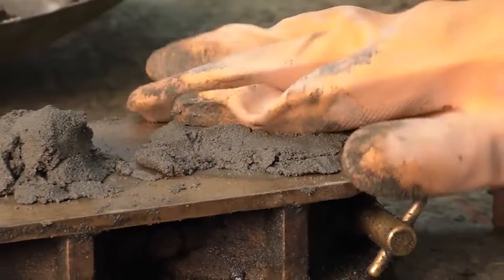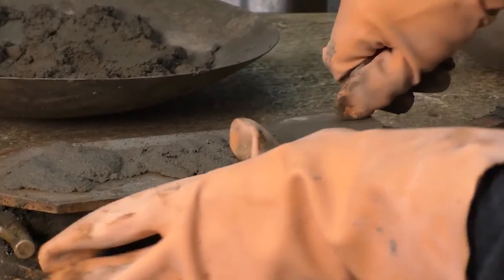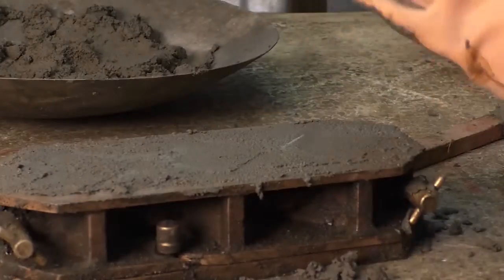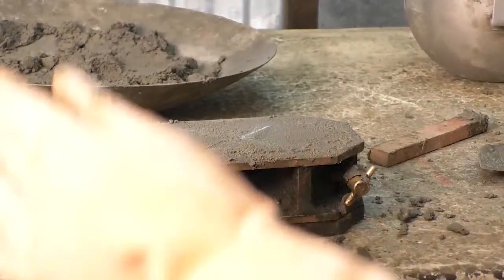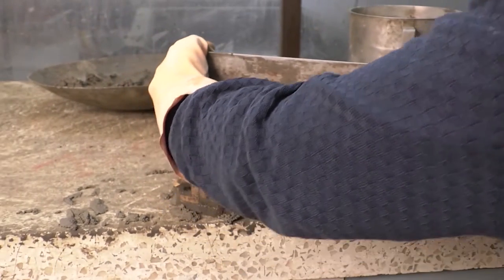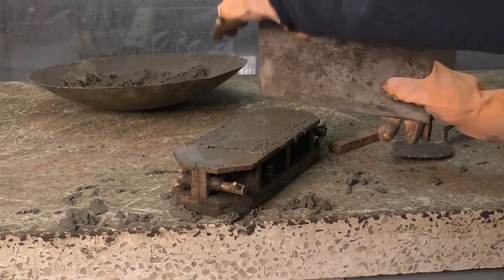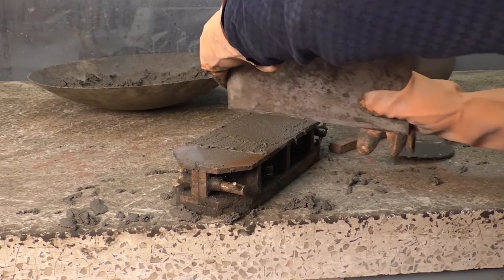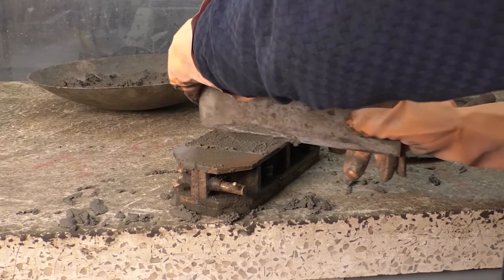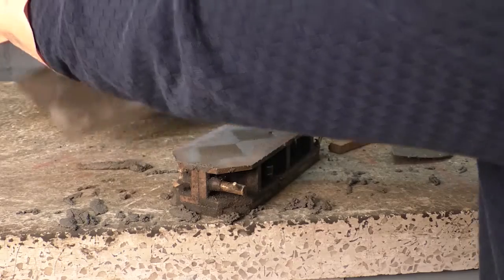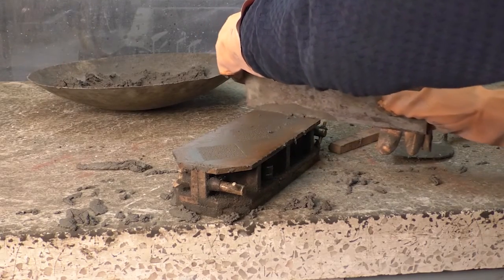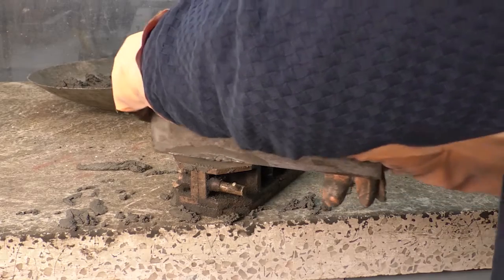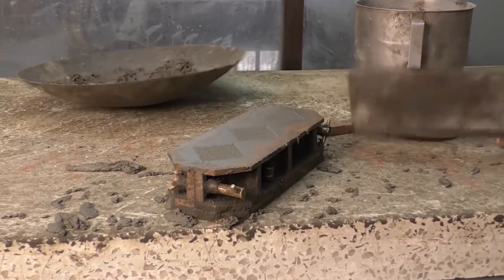We have to bring in the mortar that has been forced out onto the tops of the mold with a trowel and smooth off the cubes by drawing the flat side of the trowel. Then, for the purpose of leveling the mortar, we have to draw the flat side of the trowel lightly once along the length of the mold. We have to cut off the mortar to a plain surface flush with the top of the mold by drawing the straight edge of the trowel.